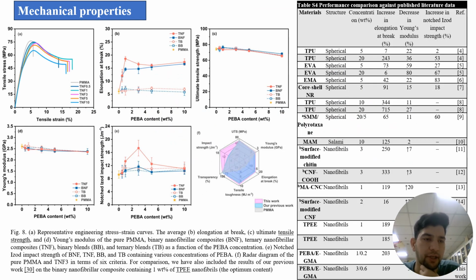Furthermore, looking at the mechanical property, it is very important for a polymer blend. Figure 8a shows the stress-strain curve comparing the tensile properties of the ternary nanofiber composites. Pure PMMA shows brittle fracture characteristics, while the other ternary nanofiber composites exhibit ductile fracture behavior with a distinct yield point and necking before complete failure.